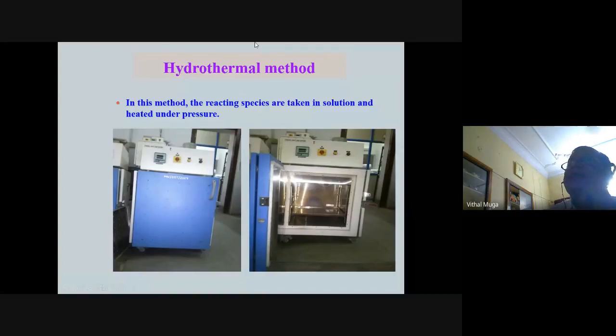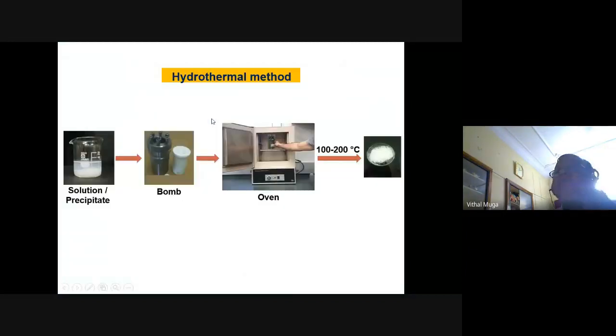Then I told you about the hydrothermal method. In this method, the reacting species are taken in solution and heated under pressure. Normally this is the solution. We transfer this into a Teflon cup, and then this cup is inserted into a steel case, and you tighten it so that air will not leak, and then put it in an oven and